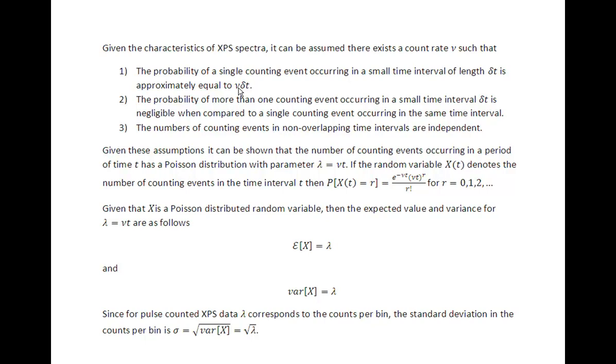That is exactly what we expect to find for XPS data — that the counts in a data bin in a spectrum are proportional to the length of time that we measure for that data bin. So the first condition is clearly satisfied.